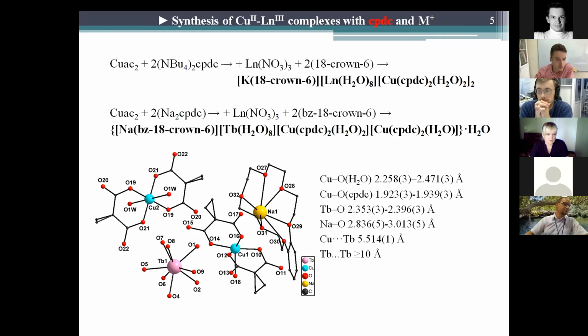When we added 18-crown-6 to the analogous reaction system, we yielded a heterometallic complex, but the structure experiment quality was very low, and we changed the ligand to benzo-substituted crown to stabilize the crown molecule in the crystal. It appeared that the complex had a similar structure with a fragment of crown ether with a sodium atom as a counter ion in the place of the tetrabutylammonium cation in the previous complex. In the main elementary unit here, one of the copper atoms coordinates one water molecule and another coordinates 2 water molecules and forms